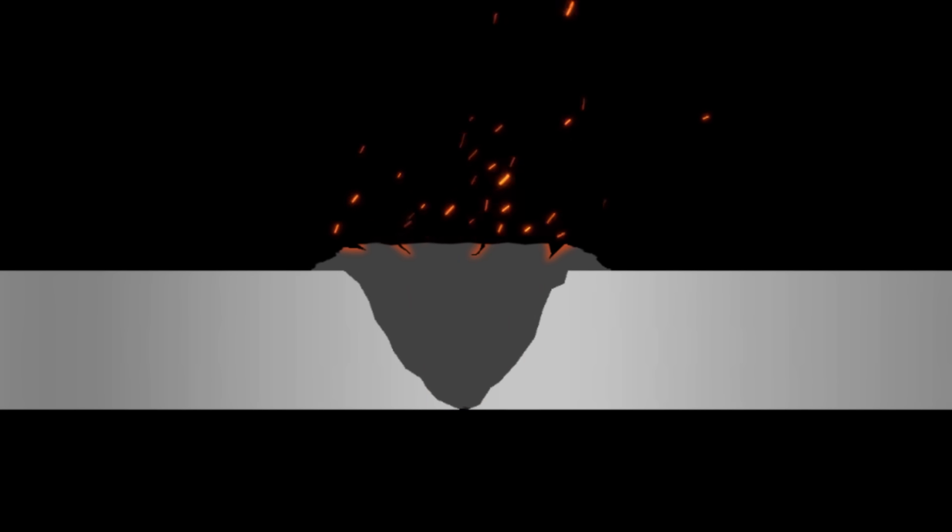These sharp edges and tiny cracks act as pressure points which could lead to much bigger cracks once Starship is pressurized. And so, grinding the surface removed these defects and reduced the chance of a weld failing.